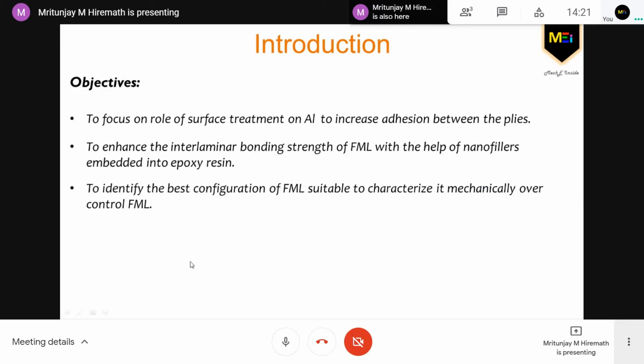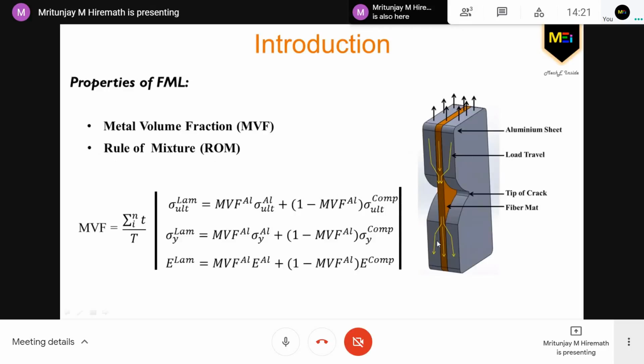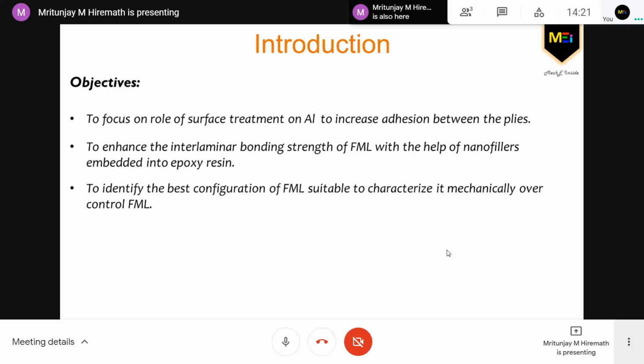The objective of ours was to focus on the role of surface treatment. As I showed earlier, the bonding between the aluminum and the glass fiber was not that strong. Therefore, we need some sort of surface treatment of the aluminum so that strong bonding exists between them, so that it doesn't fail at lower loads. The first focus is on treating the aluminum surface in order to enhance the adhesion between the plies. The second focus is to embed some nanofillers in the epoxy matrix so that we have good interlaminar bonding strength in the laminate.